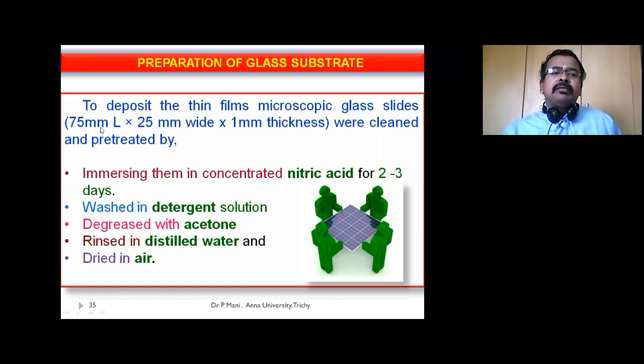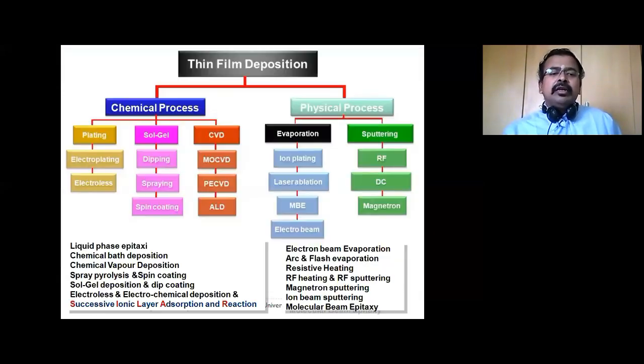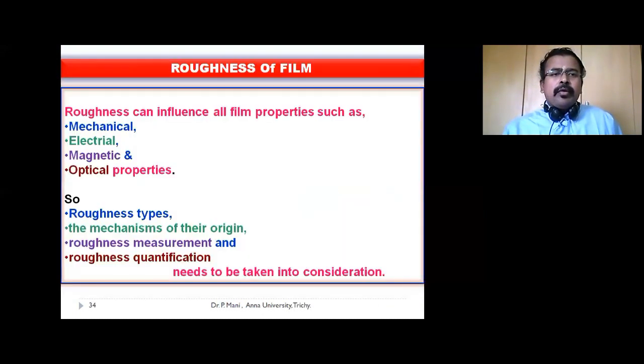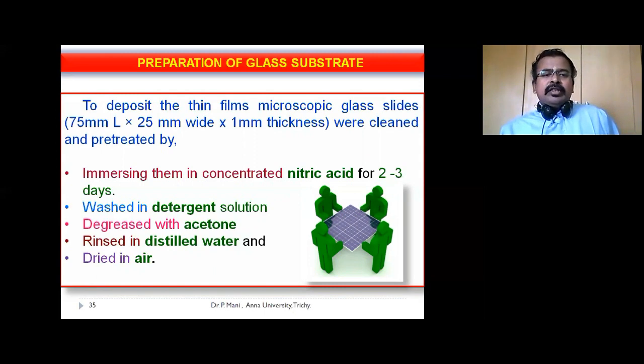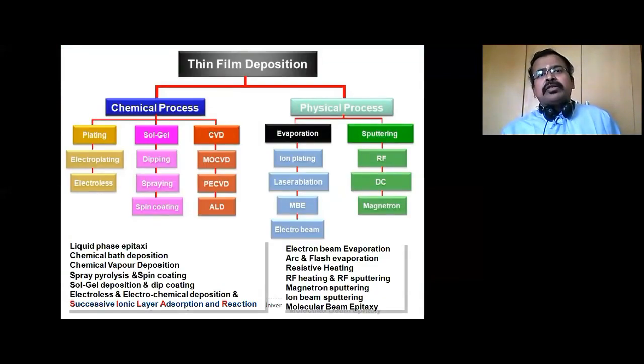The microscopic glass plates may be 75 mm in length, 25 mm in width, and 1 millimeter in thickness, and they are cleaned and pre-treated by immersing them in concentrated nitric acid for 2 to 3 days, washed in detergent solution, then degreased with acetone, rinsed in distilled water, and dried in air. So these are the 5 important steps to clean the glass substrate, and there are other steps also, such as sonication. Thin film deposition is broadly classified into physical process and chemical process.